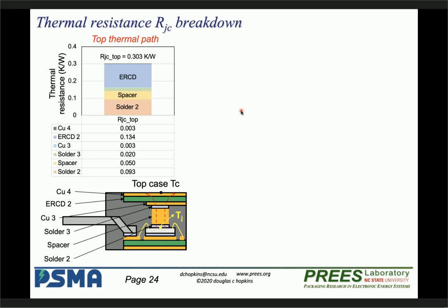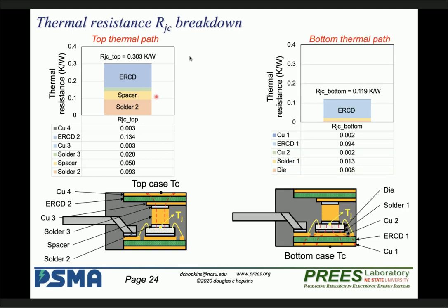Okay, so as you can see in this chart, ERCD layer contributes the major thermal resistance because of the relatively low thermal conductivity compared with solder and copper spacer material. Okay, so the right side is about the bottom thermal path. So for the RJC bottom, it is clearly lower than the top, RJC top.